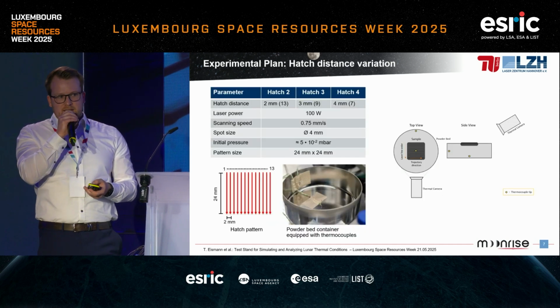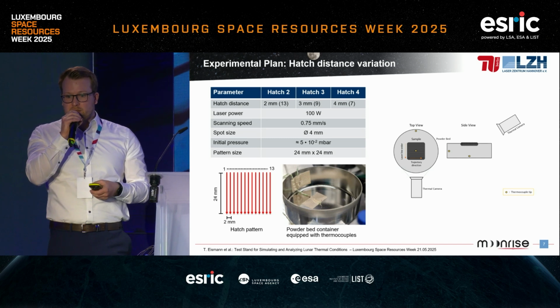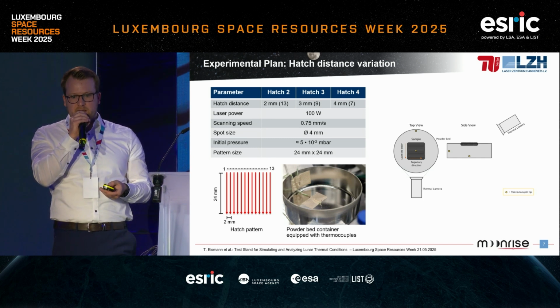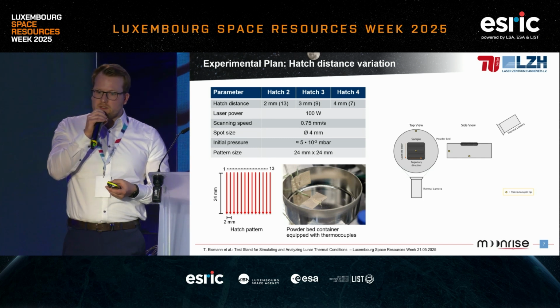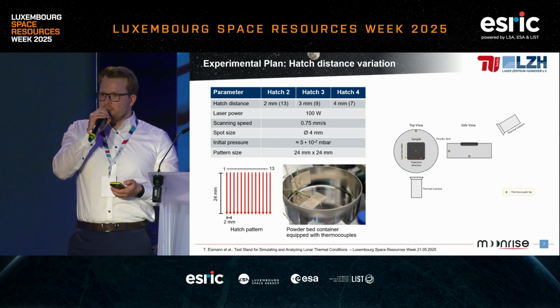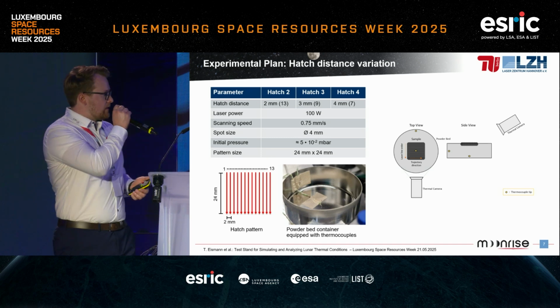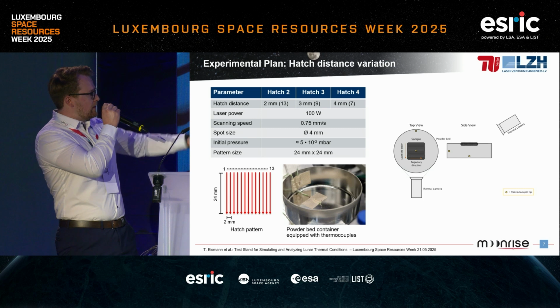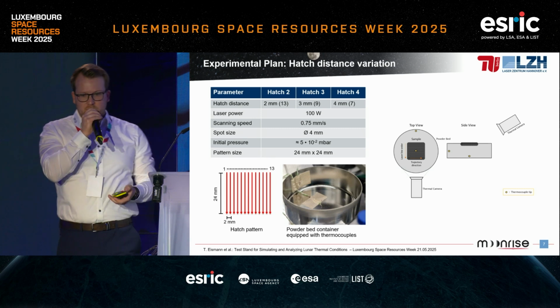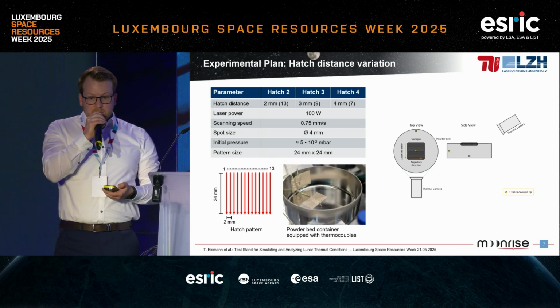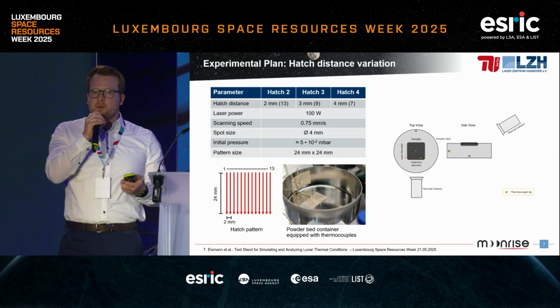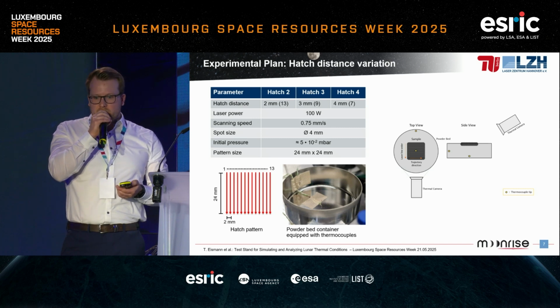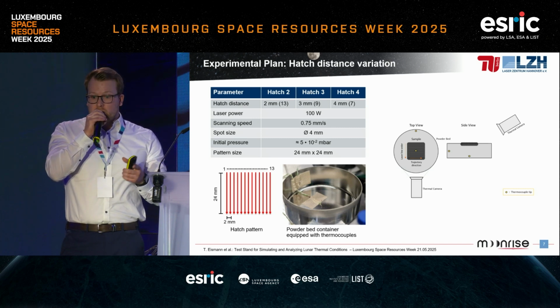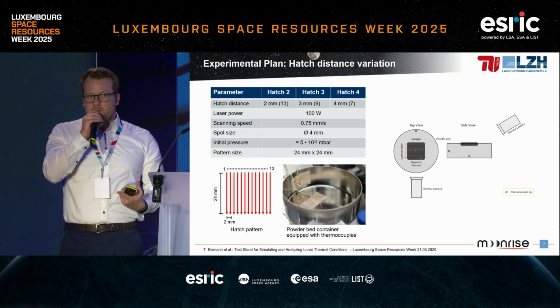And we used that setup to do some preliminary tests, just to show you what is possible with that. Our first experiment was to figure out the influence of the hatch distance, which is the distance between the scanning lines there, the 2 millimeters, for example. And we used the parameters written in the table here. And also we had two thermocouples inside the powder bed container protruding into the powder bed. And the results can be seen here.